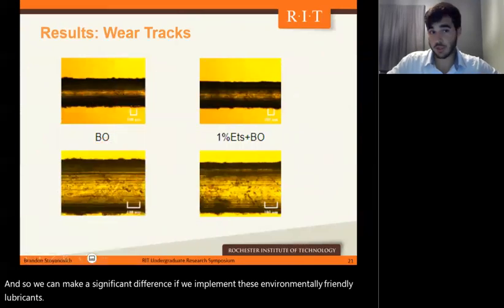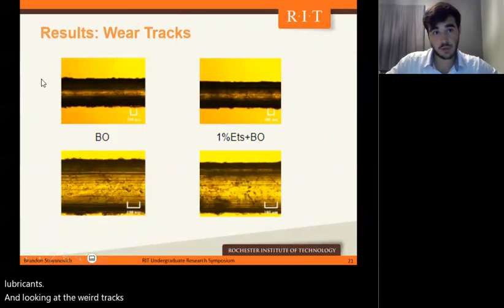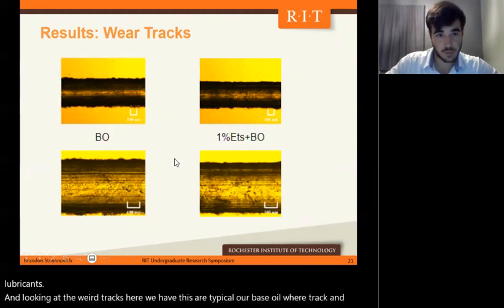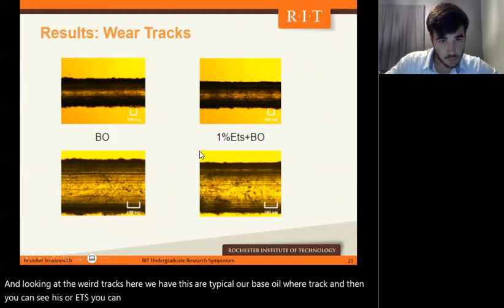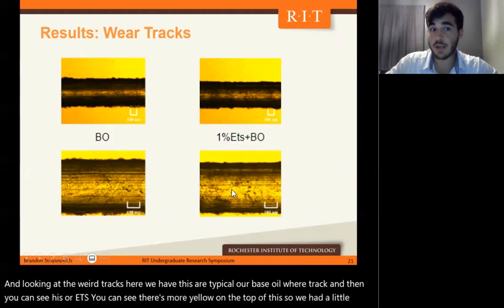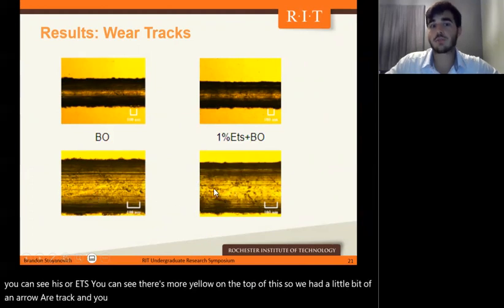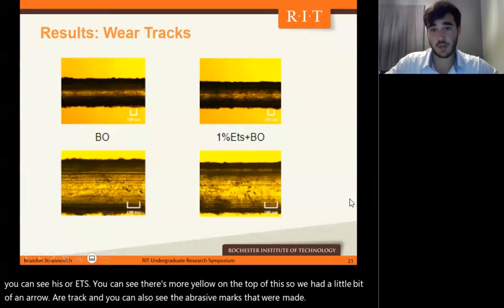And looking at the wear tracks, here we have our typical base oil wear track. And then you can see here's our ETS. You can see there's more yellow on the top of this, so we had a little bit of a narrower track. And you can also see the abrasive marks that were made in these zoomed up images here.